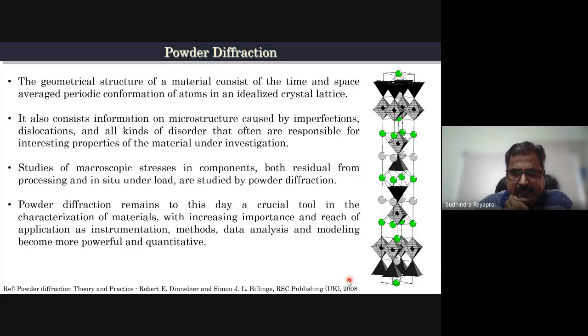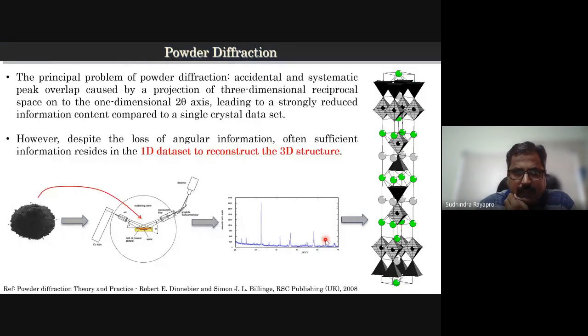And to this day, powder diffraction remains a crucial tool in the characterization of materials, with increased importance because, with the increase in the application of instrumentation methods, analysis and modeling have become powerful and quantitative. The principal problem, of course, with powder diffraction is that there is a systematic peak overlap, as you see in the diffraction pattern. Another thing is that the information you get in 3 dimensions from a single crystal is compressed into 1 dimension in the case of a powder diffractometer.